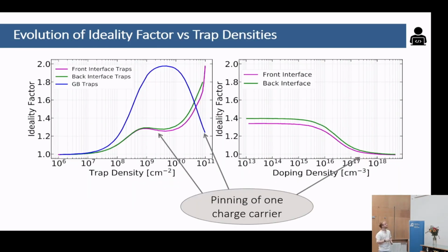And so this is some simulation I've done with different case scenarios, where you see the evolution of the ideality factor depending on, for example, the trap density, whether they are at grain boundaries, front or back interface. And then you see that at some point you can reach values close to 2, but really, in a reasonable range, you're going to see it somewhere in between. And so you need to be a bit careful.